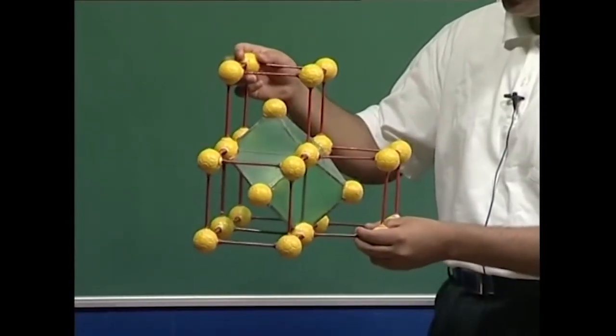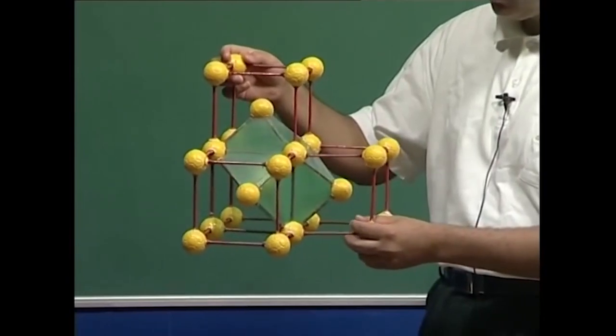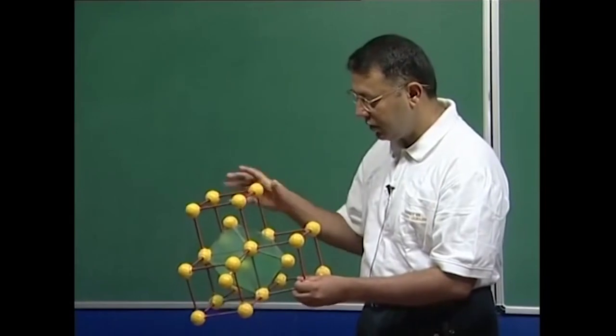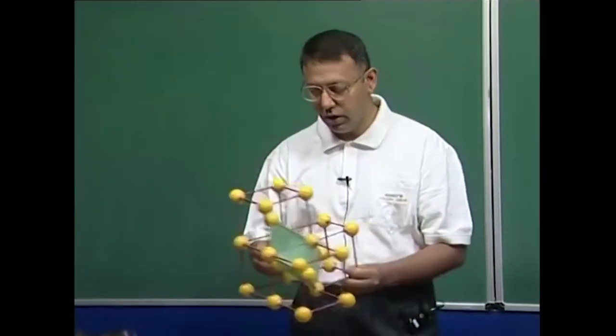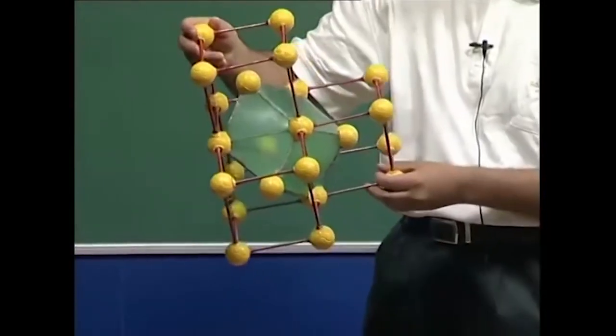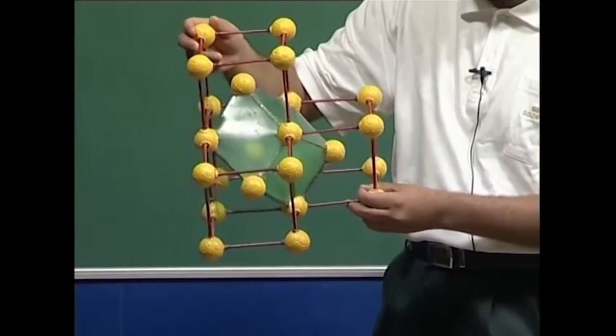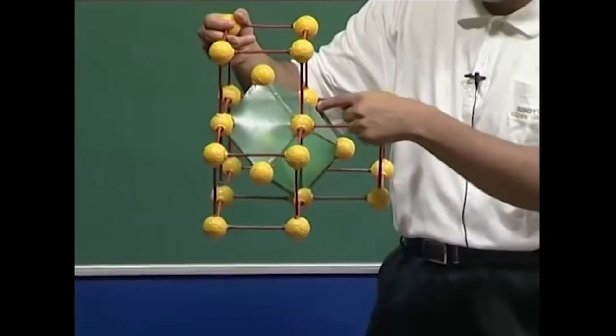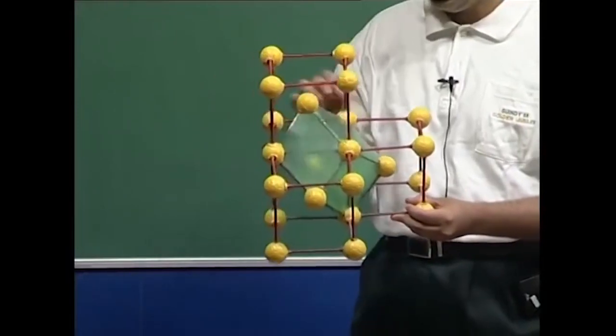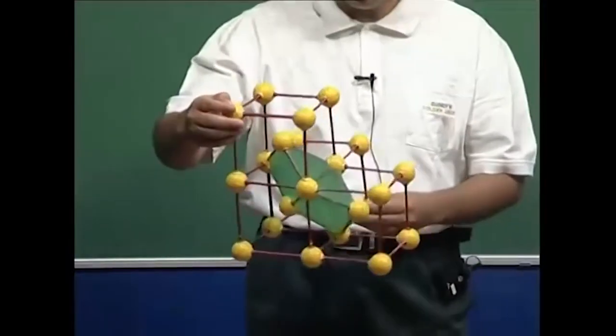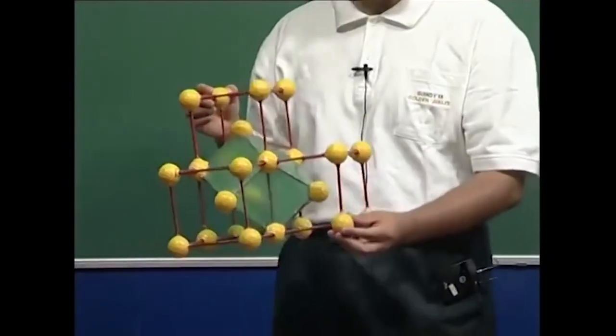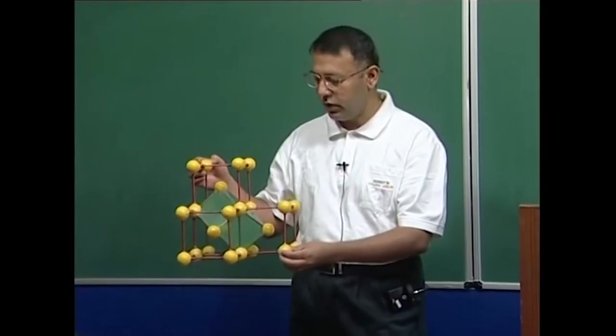The green faces form the primitive unit cell of the BCC crystal. There are 8 vertices to this parallelepiped, and 4 of these vertices are the body-centering atoms — one from the top unit cell, one from the bottom, one from the left, and one from the front. So you have 4 belonging to the BCC positions and 4 which are the original corner positions.